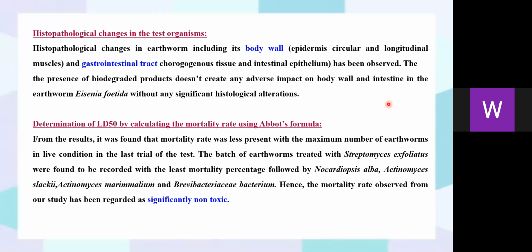Pathological changes in the test organisms. The body wall and the intestinal tract were observed. The presence of biodegraded product does not create any adverse impact on the body wall and intestine, without any significant histopathological alterations. LD50 was calculated by mortality rate using the Abbott formula. In the results, it was found that the mortality rate was low, with the maximum number of earthworms in live condition at the last trial of the test.